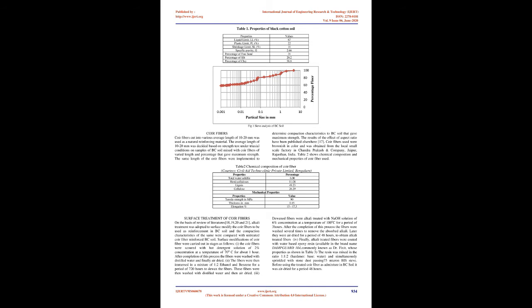Several studies have been conducted by various investigators regarding the effectiveness of surface treatment of natural fibers. Several chemical methods such as alkali treatment, acetylated treatment, permanganate treatment, and heat treatment have been tried. Alkaline treatment is among the best, as it promotes the removal of partially amorphous constituents and therefore reduces the level of fiber aggregation and makes the surface rougher 12, 13 and 14. Adhesion can be improved by surface modification of coir fiber. Further, treated coir fiber showed better impact strength 15 and 16.